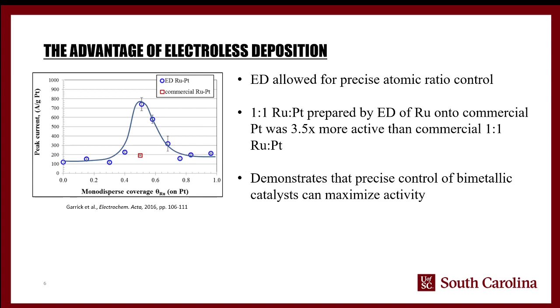And so the advantage of electroless deposition has been demonstrated previously with some work that came out of our group in 2016. Taylor Garrick showed with platinum and ruthenium, he compared a commercial ruthenium platinum catalyst, which was 50-50 ruthenium to platinum. That should be the optimal version, because for every platinum atom you have a ruthenium neighbor, and that should maximize your activity. And what he showed was that by doing this electroless deposition of depositing ruthenium onto a platinum carbon catalyst, he was able to get 3.5 times more activity than the commercial 1-to-1 ruthenium platinum. And what that demonstrates is that the more truly bimetallic your catalyst is, the more activity you're going to get, which reinforces that idea that you want to have platinum and ruthenium in this case as near neighbors to each other to maximize that catalytic turnover.